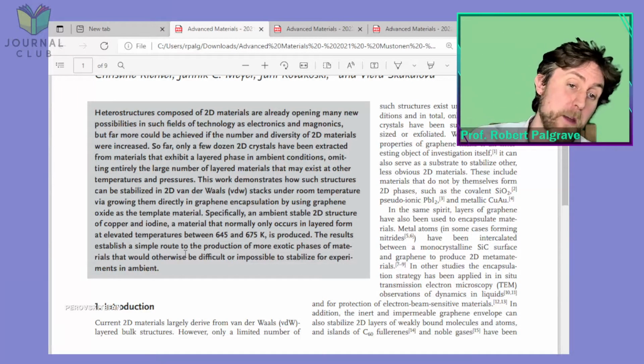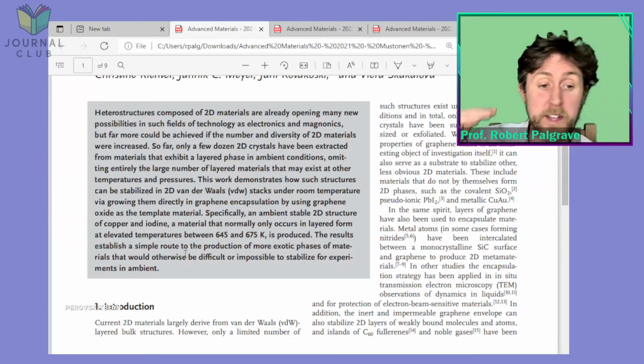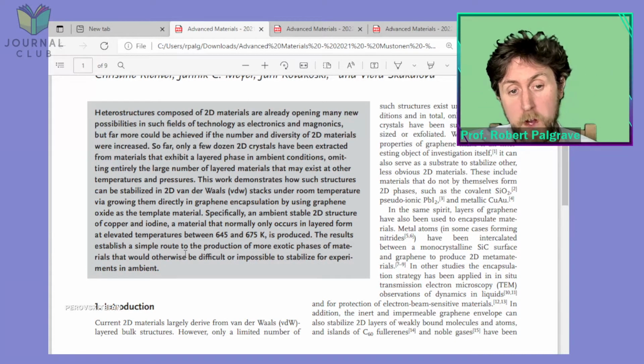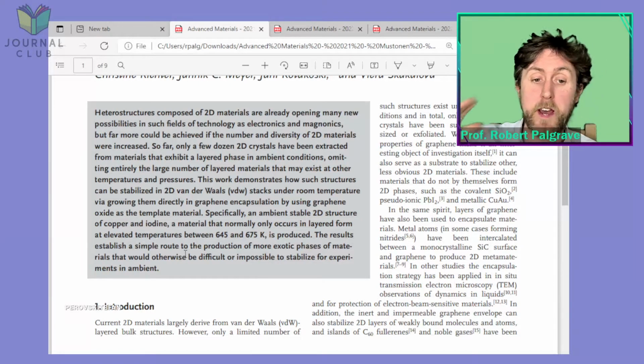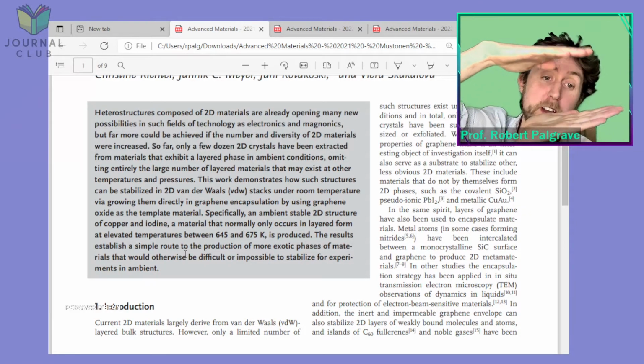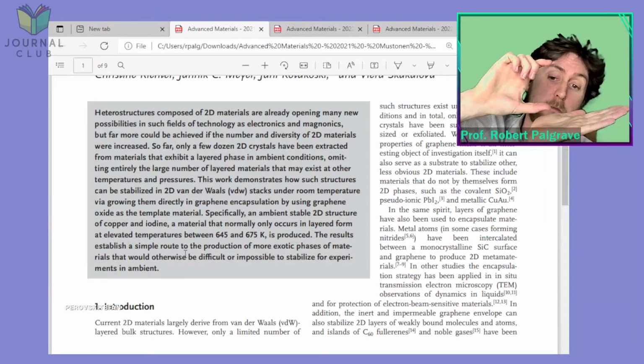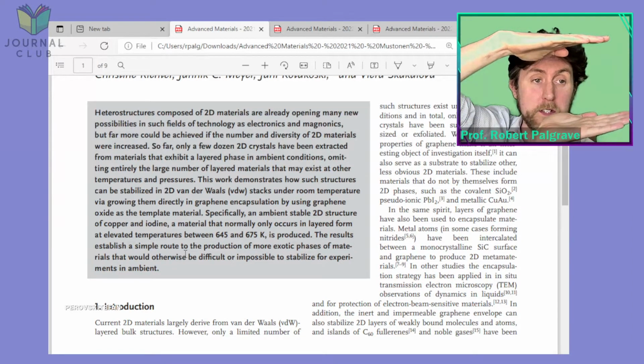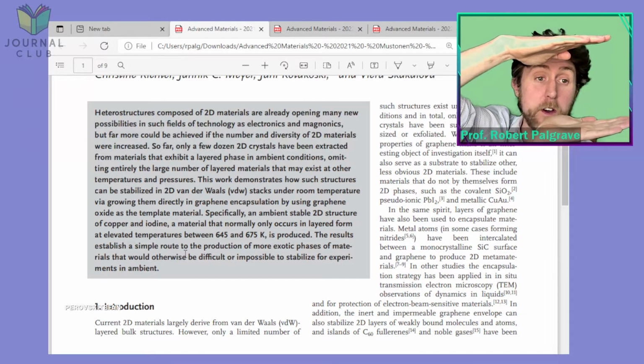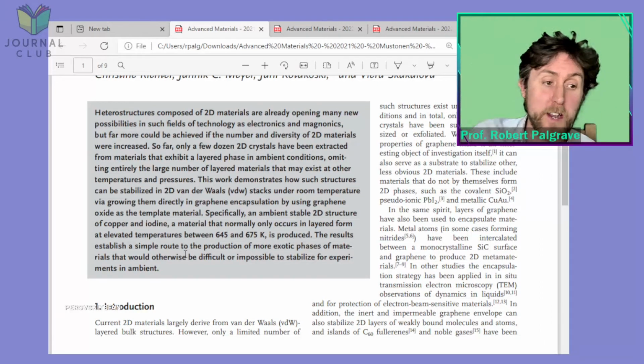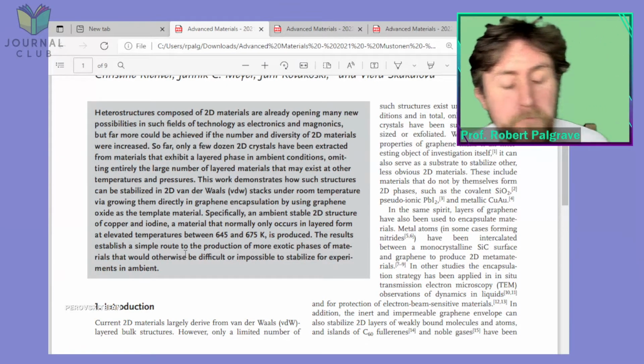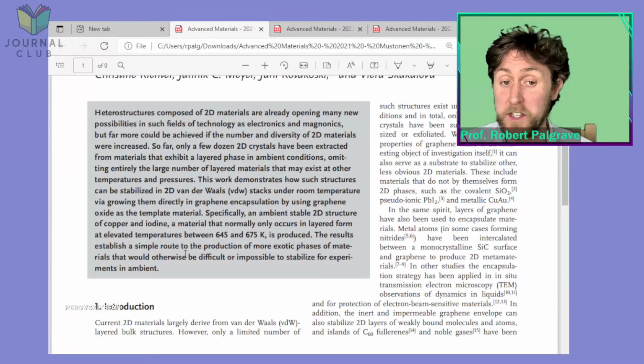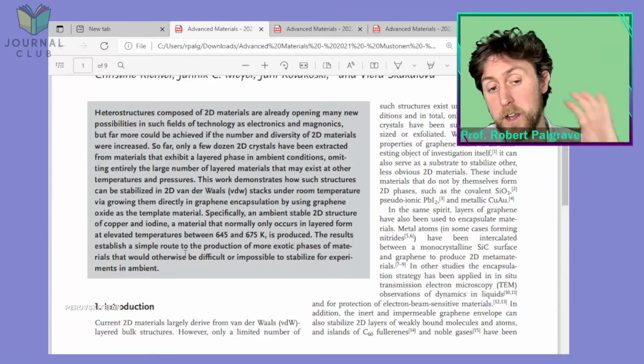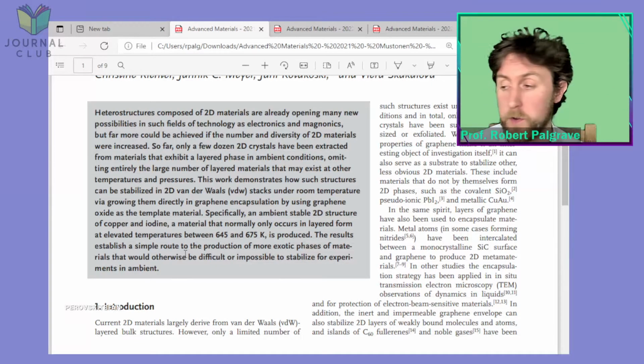But what they've done in this paper is stabilize single layers of the high temperature polymorph of cuprous iodide, and the way they've done that is they've sandwiched it between layers of that material we talked about earlier, graphene. So they've used graphene as the bread, and their cuprous iodide is the sandwich filling, whichever sandwich filling you prefer. Could be cheese, could be meat. The cuprous iodide is that part, and that's how they've managed to stabilize this layered form of cuprous iodide, by encapsulating it between sheets of graphene.